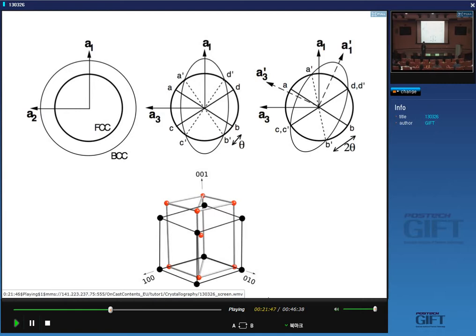That means that there is no change in the structure of the plane. It's simply shifting it by a partial, not by a lattice vector. Because if you just change by a lattice vector, you don't change anything. So it's actually a/6 <112> displacement in the 111 plane. So we know that it's possible to produce a fully coherent interface between austenite and epsilon martensite.